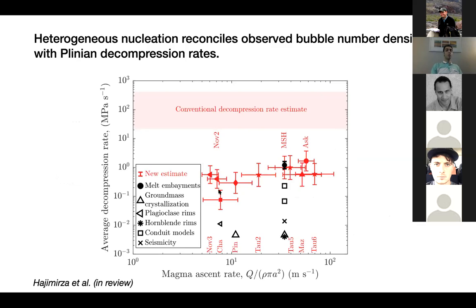We see that based on heterogeneous nucleation, these decompression rates are substantially lower than previous estimates based on homogeneous nucleation. Second, they are consistent with estimates from some independent techniques, for example, melt embayments or conduit models. So our model suggests that heterogeneous nucleation also reconciles the observed bubble number densities with the Plinian silicic eruptions' decompression rate. One important implication of heterogeneous nucleation is that